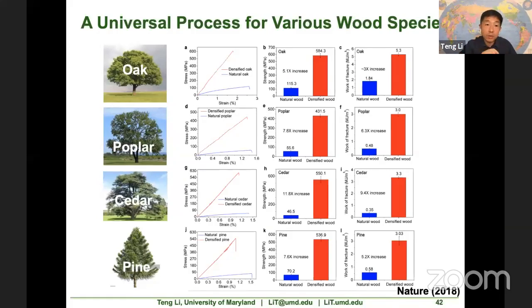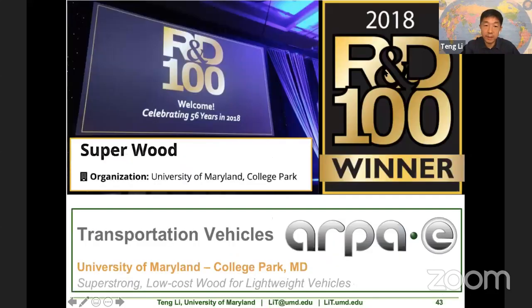Okay, so we also showed that this approach is universal for different wood species. It holds for oak and poplar, which are hardwoods, and cedar and pine, which are softwoods. It's just a matter of how many times of a difference there is, but there's always a significant increase of the strength and also work of fracture. So this piece of research won us this R&D 100 award in 2018.